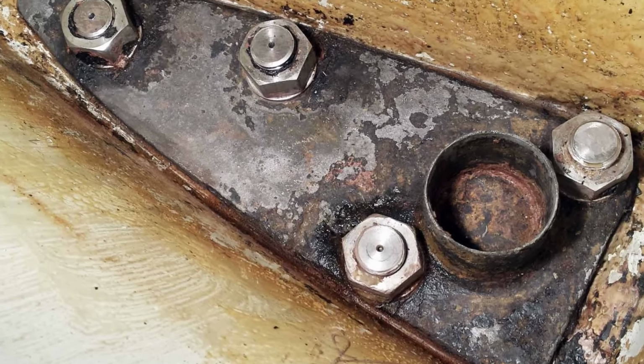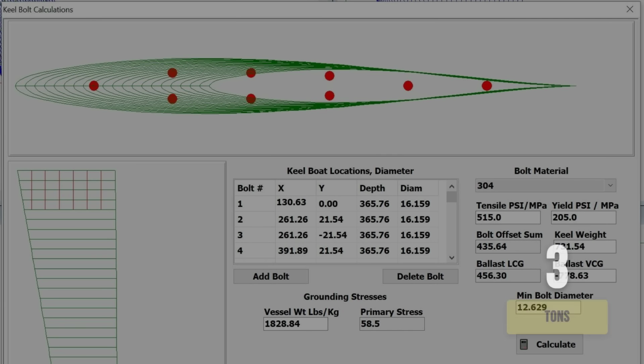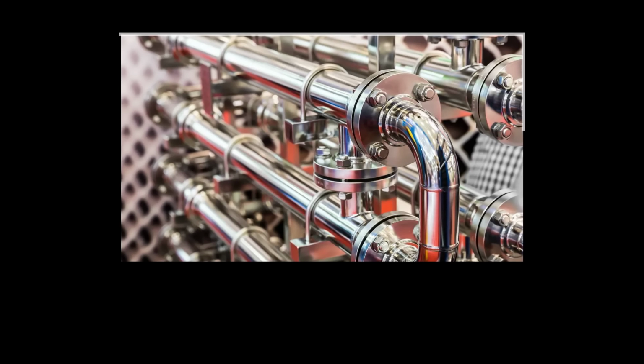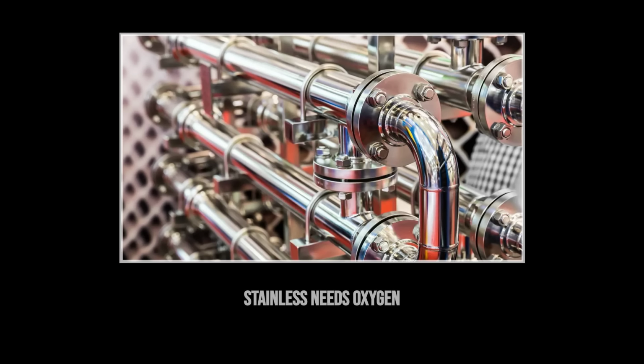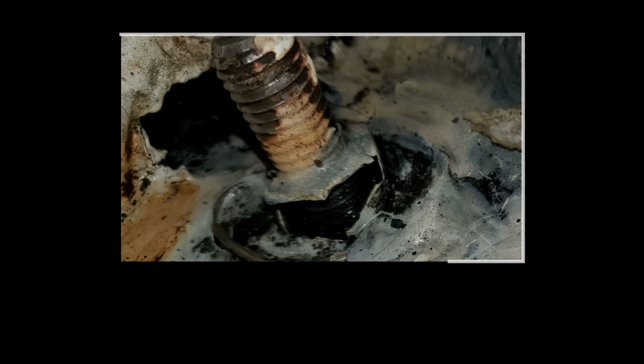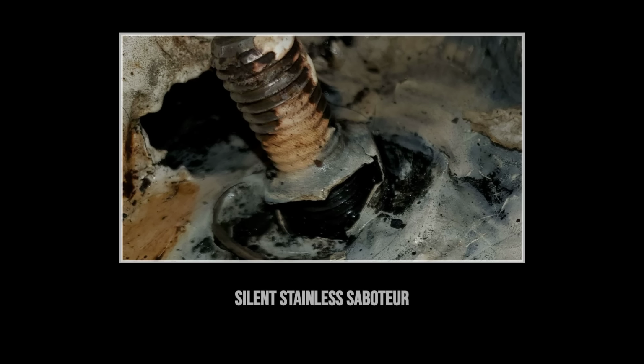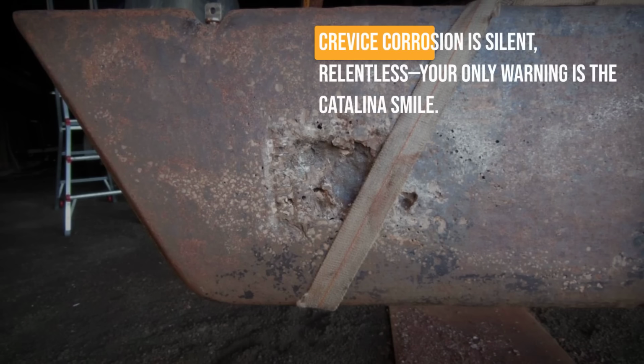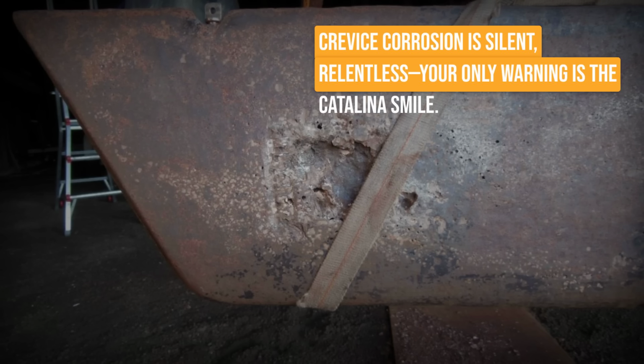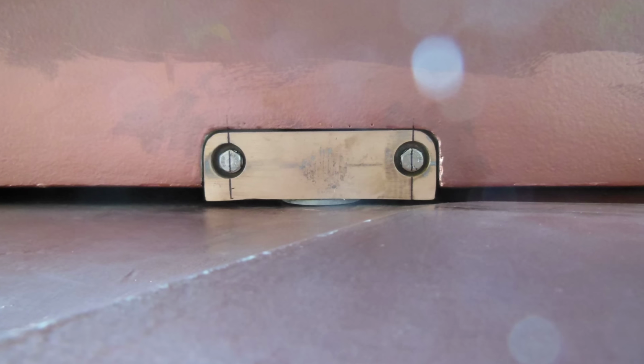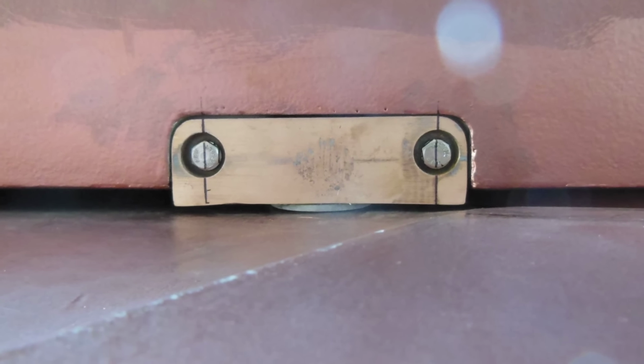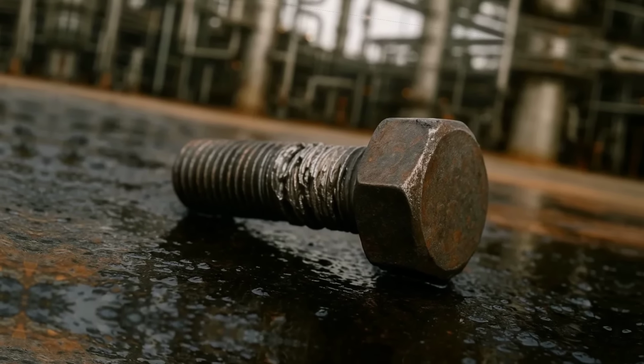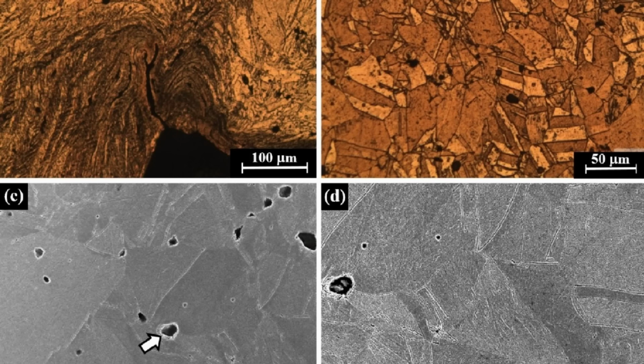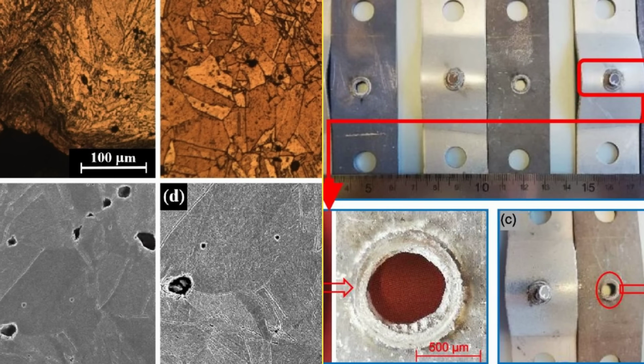Stainless steel keel bolts, buried in darkness and damp, are supposed to hold the entire weight of the keel, sometimes several tons, against the hull. But stainless steel only stays stainless in the presence of oxygen. Trapped in a wet, airless crevice, it begins to corrode from the inside out. This is crevice corrosion, and it is a silent, relentless process. On the outside, the bolt head looks clean. Inside the threads, the metal thins and pits, sometimes wasting away to a fraction of its original strength.